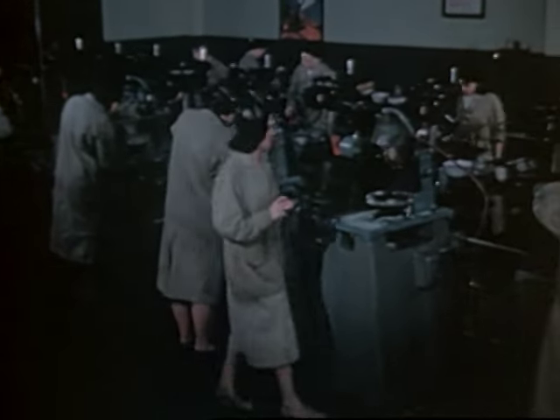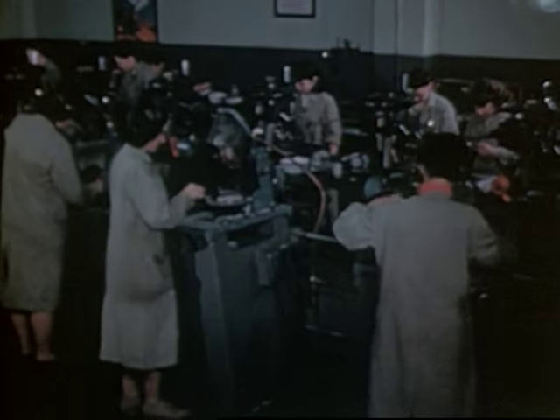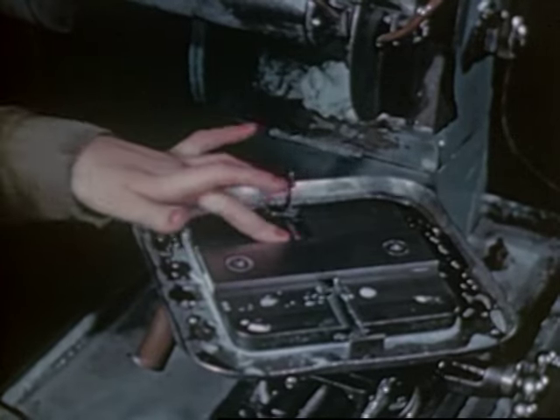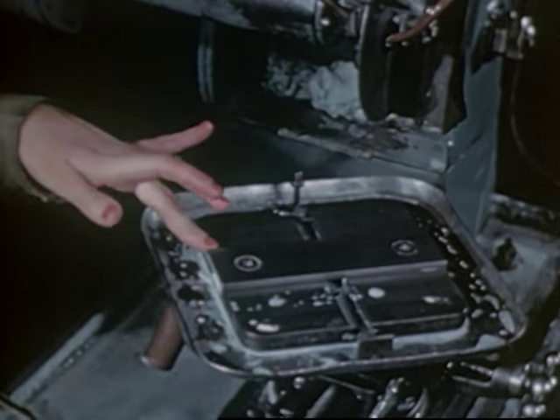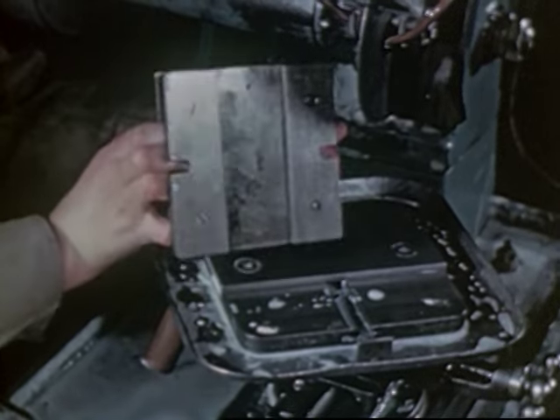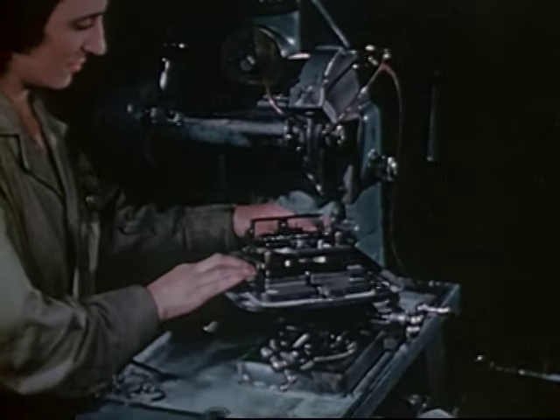In looking back, we have seen the mother crystal sawed into slabs, and one of these in turn into several bars. Wafers are next to be precisely cut from one of these bars on the basis of the electric, optic, and X-ray tests which we have just seen. On the bottom of the steel jig upon which the crystal is mounted is a groove that fits accurately into a runner on the saw table, ensuring that the quartz cut will be in accordance with the X-ray measurements.